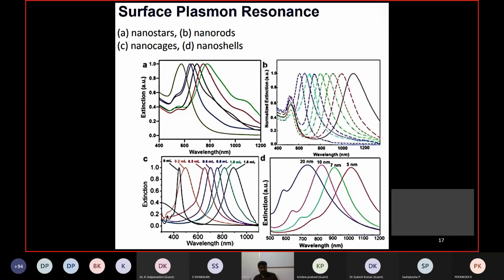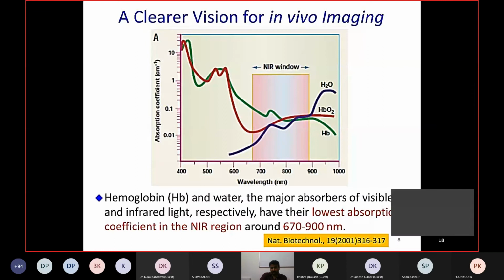808 nanometer laser. But nowadays attempts have been made to shift the wavelength even further to the NIR2 range. That means it starts above 1000. Look at the nanoshell absorption in figure D, that goes even above 1000. So there can be a laser, normally a 1064 nanometer diode laser, that can be used to heat the particles and derive the heat.